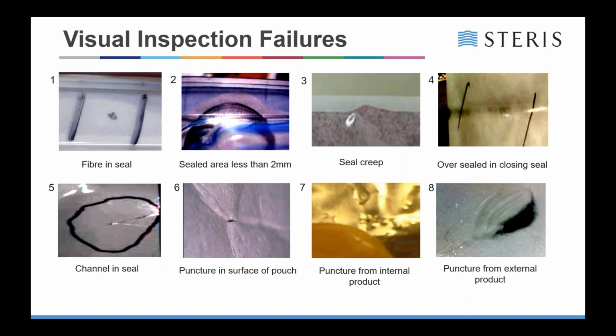Typical visual inspection failures include fibers in the seal, or the product encroaching into the seal, whereas in this instance in picture number 2, there's approximately 1 millimeter of seal left, and one good bang and that's gone. So your entire seal is breached. Seal creep is another major issue, where the seal is not strong enough to hold the product inside and the seal starts to open.